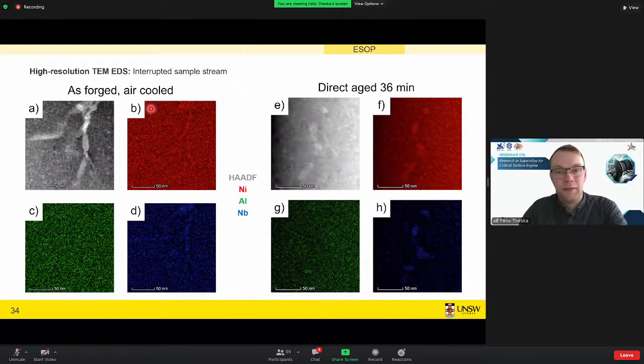So in this regard, the atom probe microscopy is better than EDX from TEM? For very small structures and very light elements, yes, because you can quantify basically any element up to hydrogen. Hydrogen is difficult, but that has something to do with the vacuum system of the machine. Okay, because we have no atom probe microscopy, I think, in Indonesia, so it's very interesting. Okay, elaborate, yeah.